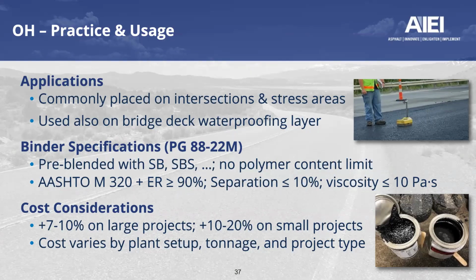They are utilizing the PG AASHTO M320 with an elastic recovery of at least 90%. They have a separation requirement of no more than 10%, and the rotational viscosity has a relatively high allowance, compared to most PG binders, of no more than 10 Pascal seconds.